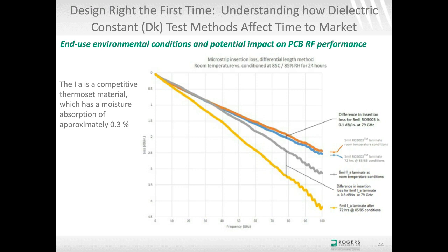For the RO3003 circuits, there's a difference of 0.1 dB per inch at 79 gigahertz, and the difference in insertion loss at 79 gigahertz for the competitive material is much more, about eight times more, about 0.8 dB per inch. So moisture absorption can really be a big deal, even with numbers as low as 0.3. In the case of RO3003, the moisture absorption is very low at 0.05.